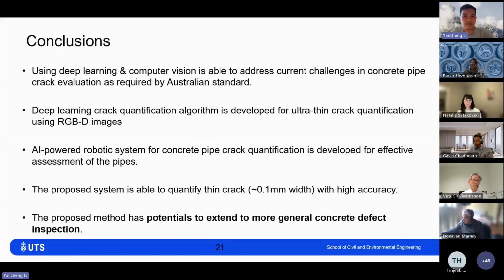And in conclusion, of course, we use an RGB camera and a multimodality deep learning algorithm to quantify ultra-thin cracks in a pipe. We also have an AI-powered robotic system for concrete pipe crack quantification, and this system is able to quantify thin cracks, roughly 0.1 and even lower, with high accuracy. Worth noting, we have the potential to extend into other types of concrete defects. We are doing this as well, including corrosion, other types of discoloration, and spalling, etc. We will also be able to do it.